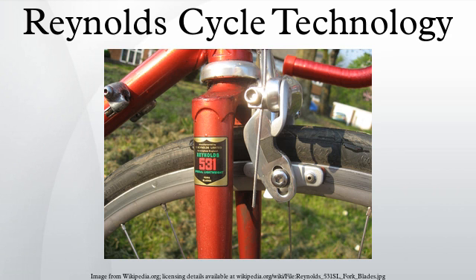921, cold work stainless steel. 931, precipitation hardening stainless steel. Tubing introduced in 2012. Can be used with 953 to reduce overall frame costs. 953, maraging stainless steel. Introduced in 2005. UTS 1750 to 2015 MPa, density 7.8 grams per cubic centimeter.